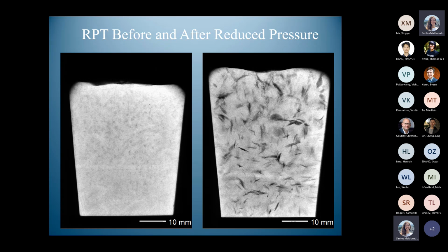And in this way, if now I solidify this liquid metal into the solid, and now I stress the solid, this isn't going to do much because it's a very ineffective crack in its scrambled form. However, if I now reduce the pressure on the outside, then this crack opens, fold by fold. It takes time. Each fold takes 10 or 20 seconds or something like that. And slowly, slowly, slowly, it gets bigger and bigger. And finally, it's now a rather serious engineering crack, a bit uphill and down dale. Notice it's got kinks and things in it.